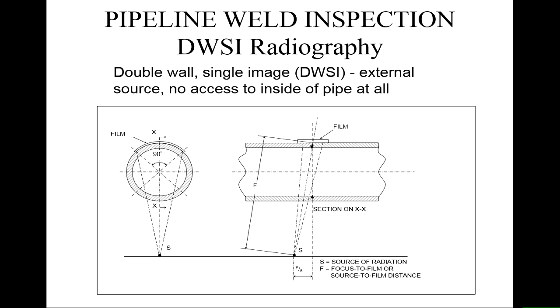If you take that a little bit further, you can put the film on just the back side of the pipe, and from a single source angled to the pipe, you can capture on one film what's happening on the front wall and on the back wall of the pipe. So if you looked at it like so, this is a straightforward case. The defects in here are being tested, and the defects in that larger range are being tested. But in both cases, the X-rays pass through two lots of wall, and you get an image from both sets of defects on one plate.